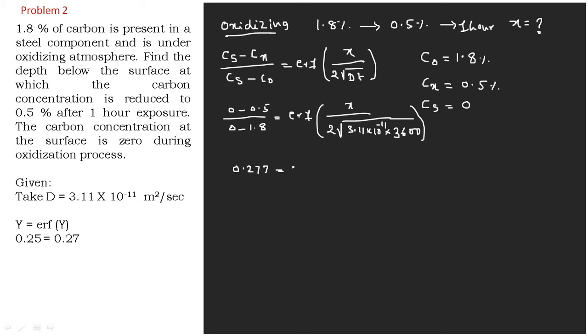Let us say that the whole value in the bracket is equal to Y. We got erf(Y) = 0.277. From the table we find that the value of Y is 0.25.